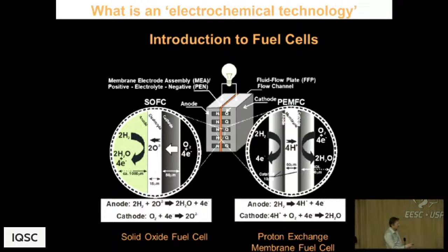None of these materials have an infinitely high conductivity. They have a finite conductivity. So we have a resistance of the membrane associated with its ability to conduct protons. We have a kinetic resistance associated with the electrochemical kinetics of these reactions, which are measured by things like exchange current densities and so on. We have materials that have to conduct electrons that have finite conductivities. So again, we get some resistance. So we have a resistance of the cell. As the current goes up, the voltage goes down.